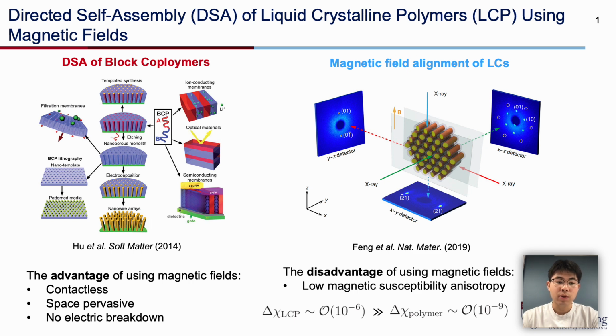The reason why we use magnetic field is it's contactless, space pervasive, and it doesn't have electric breakdown compared to electric field, which makes magnetic field very intriguing from the perspective of scalability, and also it allows us to approach the sample surface in any field direction. But the main problem of using magnetic field is most soft materials don't have a high enough magnetic susceptibility and anisotropy, which means they're not responsive enough to magnetic field.